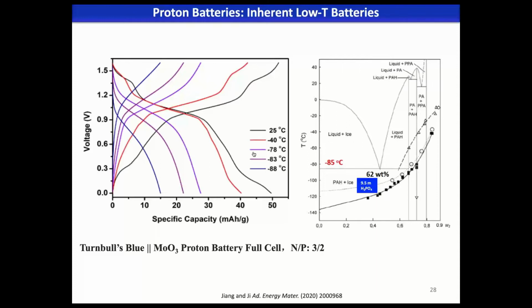Why not study its low temperature behavior? We know the Arrhenius equation, and also the activation energy and the temperature. There are all kinds of correlations, and temperature is really important. When the temperature is lower, you're going to have sluggish reactions. Now, we see the proton works even at minus 88 degrees Celsius. Of course, in this case, we have to use a really concentrated phosphoric acid.